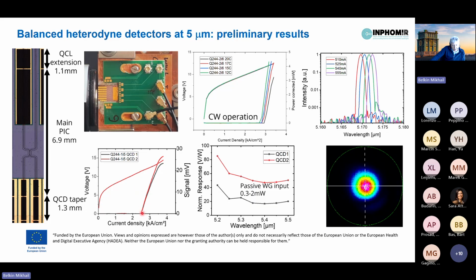This is the readout of the detectors as a function of pump current of the laser, on a slightly different device, so the threshold current density is a bit lower, but nevertheless you can see close to 50-50 splitting. And then we could also couple light through the passive waveguide and also observe the detector signal in detector 1 and detector 2. Here we are not too close to 50-50, probably because of some fabrication defect, but nevertheless, even this splitting is sufficient for demonstration of balanced heterodyne detection, and this is now as a function of wavelength. We also can measure the far field profile of the laser to confirm that this is really operating in TM00 mode. Now this chip has just been shipped to our partner, GEM, for actual characterization of its performance in the heterodyne regime.